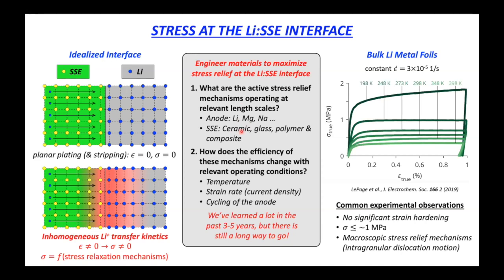That's obviously going to play a major role in stress relief as well. And there's a bit of a whopper of a challenge in there, because the stress relief mechanisms in the separators are obviously going to be really different as we go from ceramic to glasses to polymers and composite materials, right? So there's a lot of moving parts in there. And if that wasn't complicated enough, then we also need to know how the efficiency of those stress relief mechanisms is going to change with operating conditions like temperature, current density, and cycling of the anode, right?